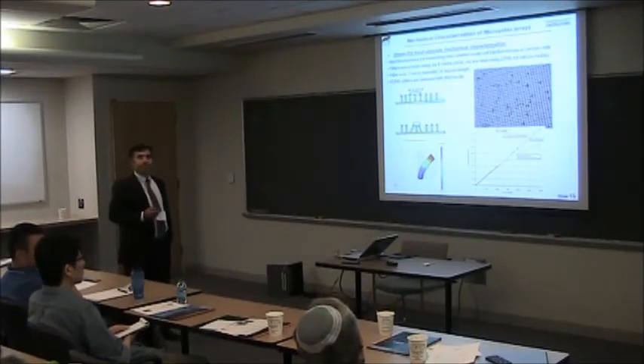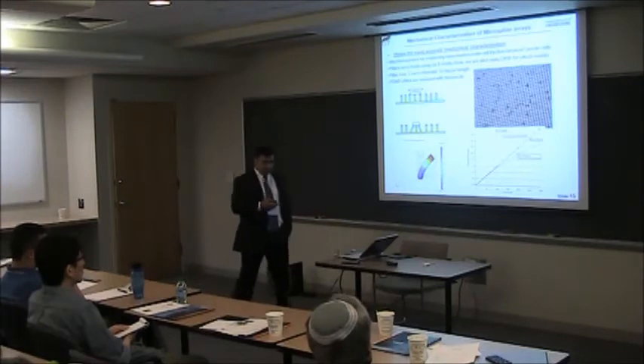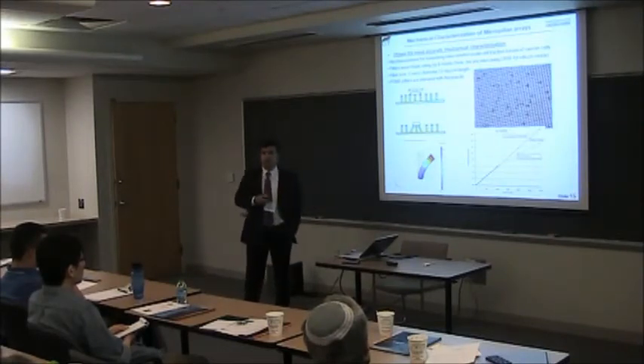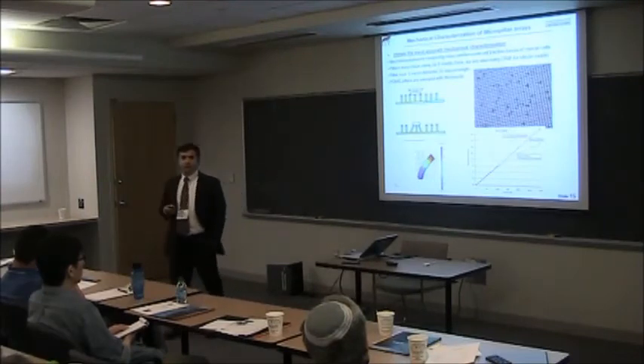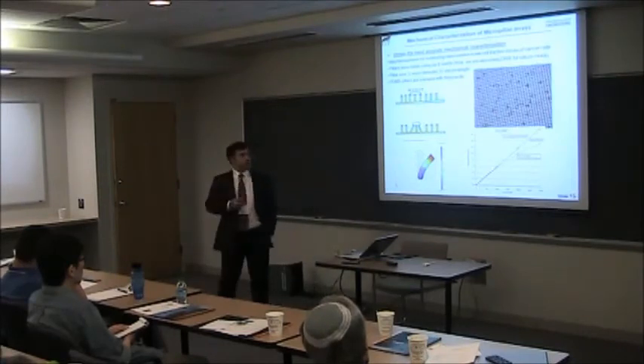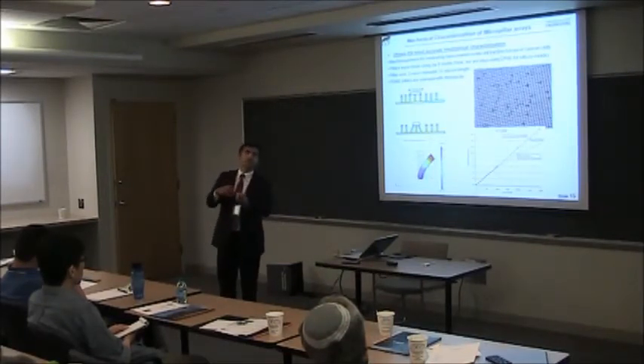Excuse me. You have the cell. Is it covering more than one pillar, right? Yes, 3 pillars. In fact, in the literature, right now we have 5 micron diameter, 20 micron tall. In the literature, there are 3 micron diameter and 9 micron tall as well. But they made those using deep reactive ion etching, which we have now. We are making them too. But the idea is, if you have the pillars dense enough, you can assume that the cell is actually moving on a flat surface. That's the basic idea.